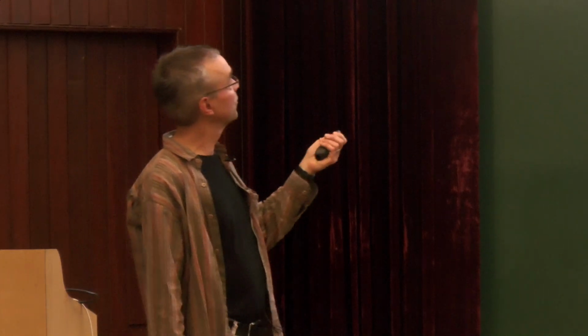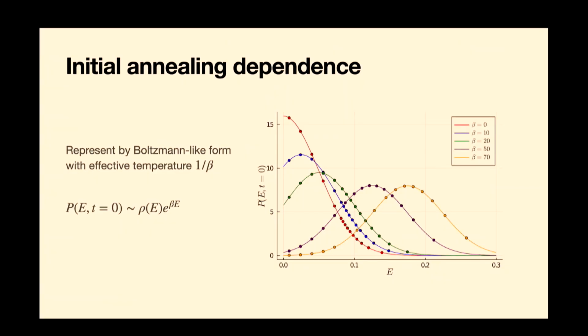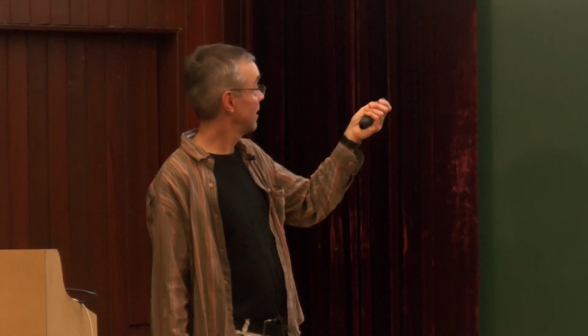And so for the theoretical analysis, what we're going to assume is that the initial annealing is represented by a sort of Boltzmann-like annealing factor on our yield energy distribution. There's no minus here because I'm counting the yield energies downwards in some sense from a reference energy, so therefore there's a plus sign here. So this parameter beta will tell me how well annealed the sample is. Beta equals 0 is something that's basically just been stirred, and has the sort of prior distribution of yield energies. Beta, the largest value that we look at, is 70, something that's very well annealed. Most local regions have very high yield strains in that system.